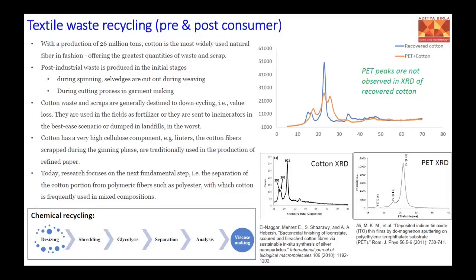So this graph talks about the XRD pattern, and this shows that when there is a mixture of PET and cotton, this is how the XRD is formed. And we know that for cellulose we have a very sharp alpha cellulose peak at 21.7 theta value. So when we separated or recovered the cotton, we got a very good separation of cotton, wherein we did not observe any PET peaks in the recovered cotton.